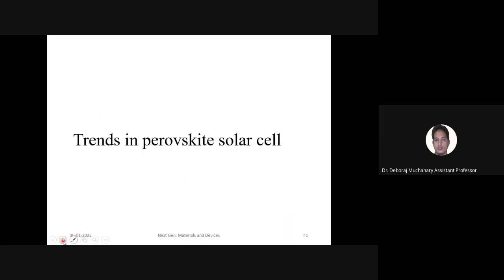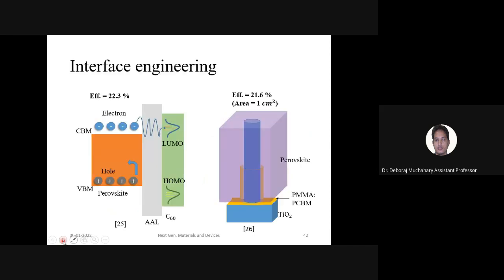Now, trends in perovskite solar cells. What I have found as a trend in solar cells is, first of all, interface engineering. What is interface engineering is that we know that a perovskite solar cell has one side, the electron transport layer, and another, the hole transport layer. Here what we have seen is between this C60, an electron transport layer, and this perovskite layer. In recent work, in 2025, they have given this AAL layer. Some chemical compound they have used, and conceptually I'm showing that these electrons are tunneling through this AAL layer, which is some dielectric layer.